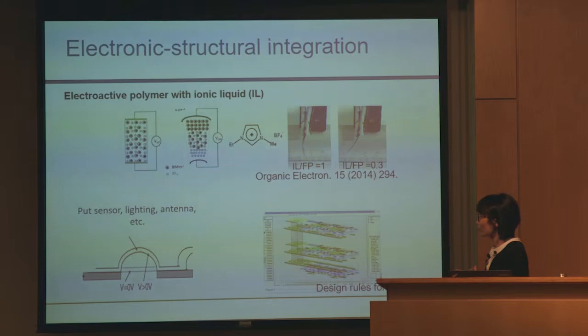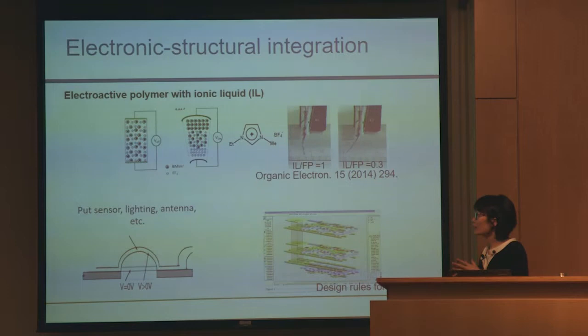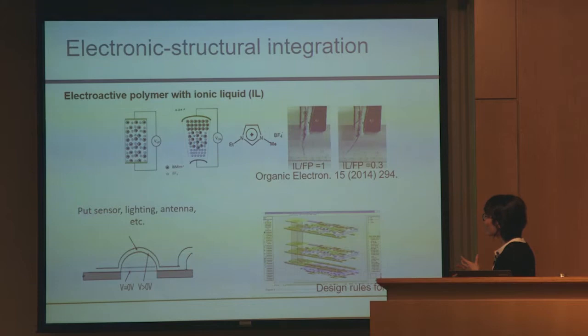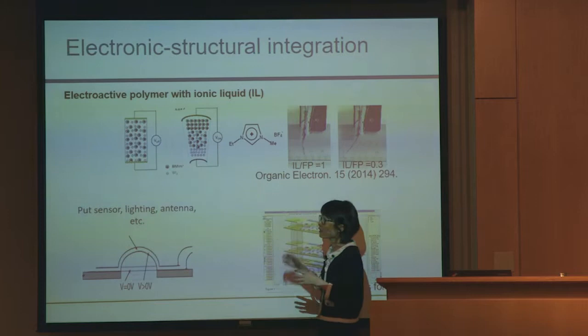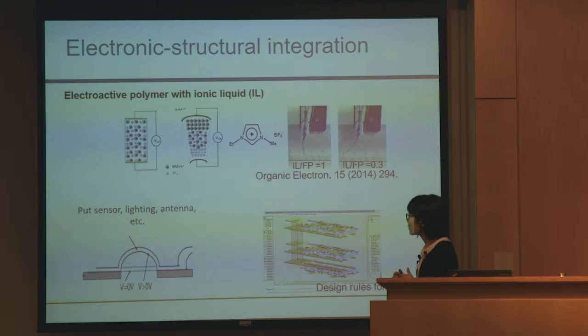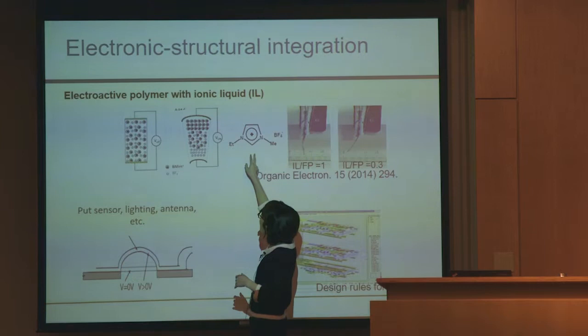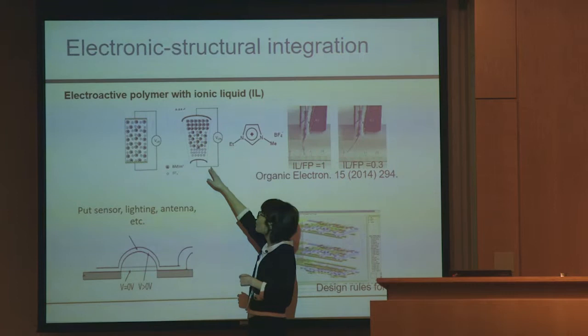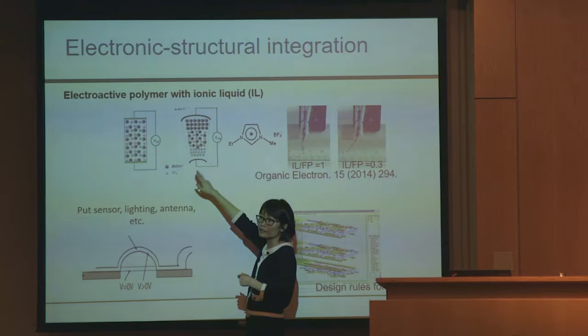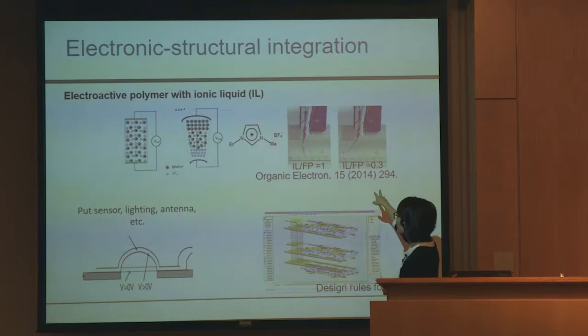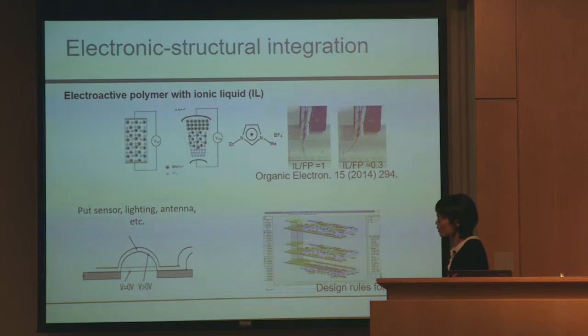Being a material scientist, one of the materials we could use is this ionic liquid. It's a new kind of salt, in the sense that it's always ionic, but it doesn't evaporate, and it has a lot of interesting properties. By putting that into a hydrogel, a polymer host, and then applying a voltage, the ion sizes are different. Once you apply a voltage, the cation moves to one side and the anion to the other. Because of the size difference, one side swells and one side shrinks. Just this simple mechanism lets us make actuators like a bimorph and bendable structures.